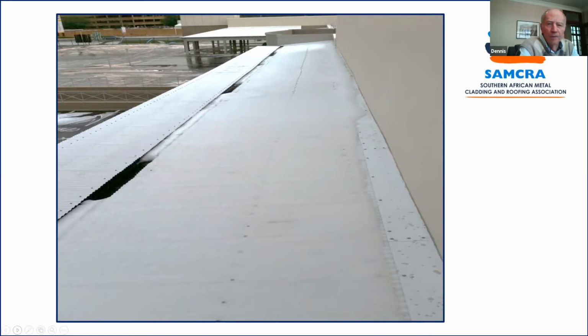Now, if you look at our first visual, this was a shopping centre out in Klerksdorp, and you can see where the downpipes are, because that's where the black holes occur. But you can see on a flat roof, the small hail accumulates, and it accumulates very rapidly. And the problem with small hail is it's normally preceded by a brief or perhaps quite an extensive shower of rain. So the first bits of hail that start to fall on the roof end up being washed into the gutter and block up the gutter and affect its performance.